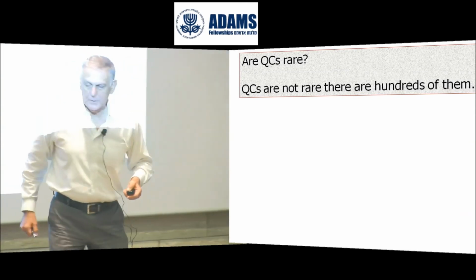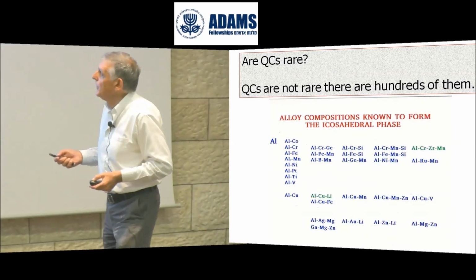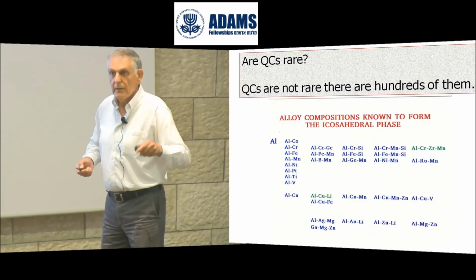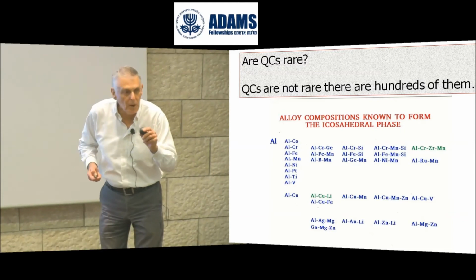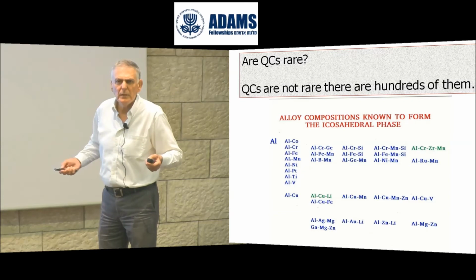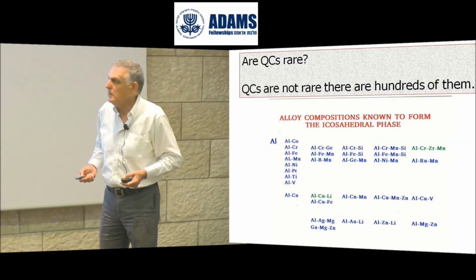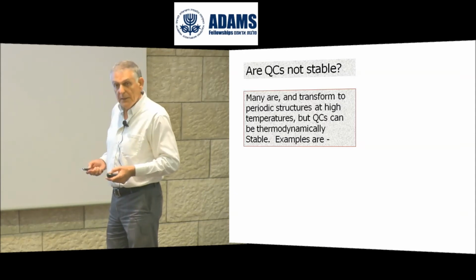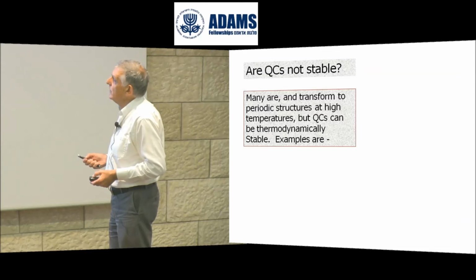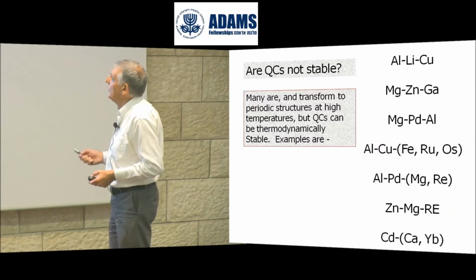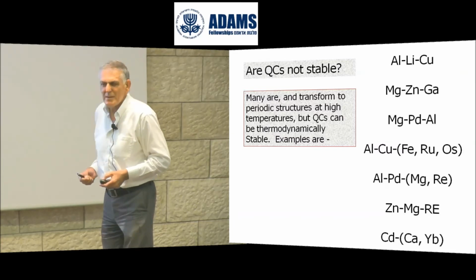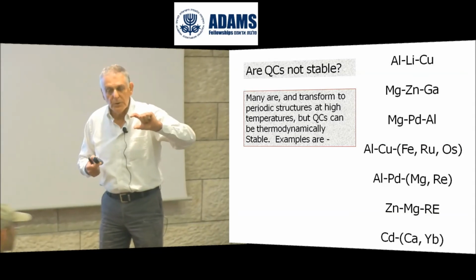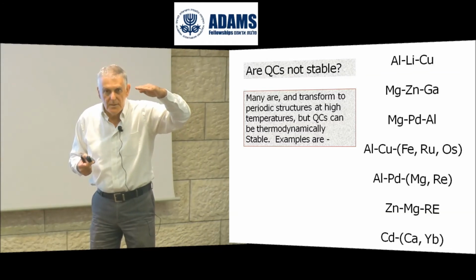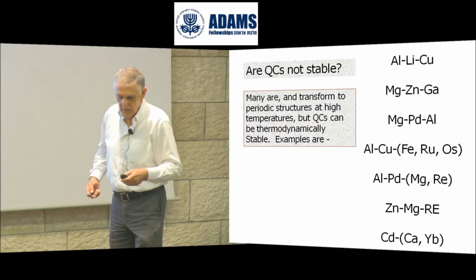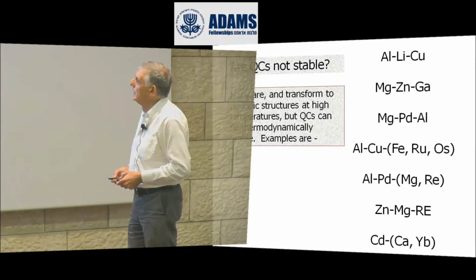Here's an example. This is a partial list of quasi-periodic materials based on aluminum alone, and there are many based on other elements. There are hundreds of them. That's not the reason they were not discovered before. Are they not stable? Many are stable, and some transform to periodic structure at temperature. But quasi-periodic crystals are thermodynamically stable, and here are a few examples of thermodynamically stable ones. But also the ones that are not stable, what does it mean not stable? They transform into periodic crystals when you heat them up to 400 degrees C. But at room temperature, okay, no problem. So this is not the reason that they were not discovered before me.